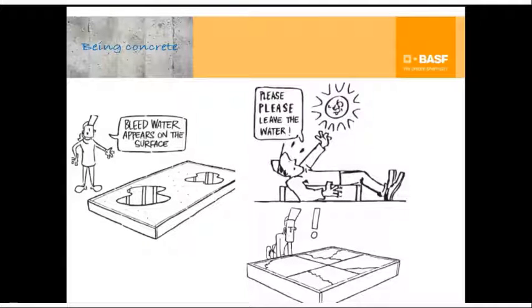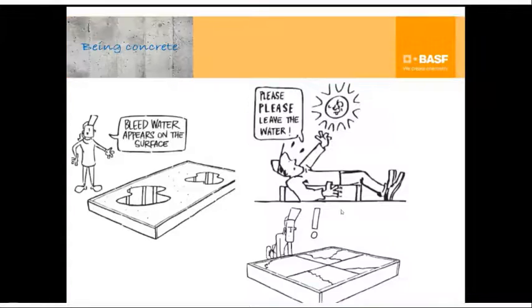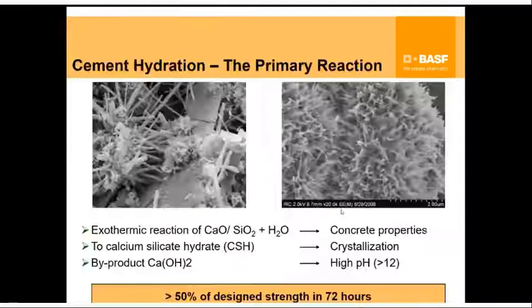However, if you see bleed in conditions where these aggressive environments are not there, then you may have some issues on the top surface. So again, it's a tool that you have, and you need to be able to use this properly. Otherwise, as I show in the next slide, you could have shrinkage cracking, and bleed can prevent some of that cracking under these aggressive conditions.